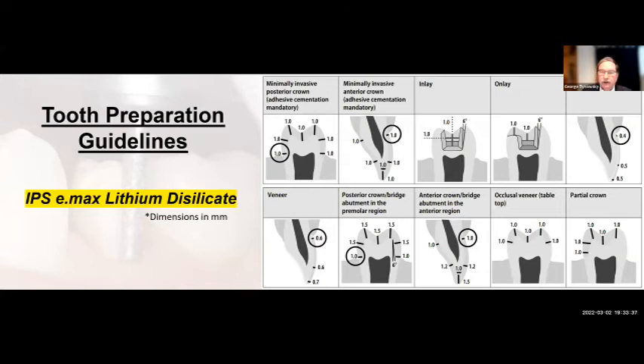Let's briefly take a look at some of the elements. We want rounded line angles and clearly defined margins, so the machine can visualize them from our scanning or impression techniques and can actually mill the margins accordingly. If we have an adhesive crown for lithium disilicate restorations, we can bond them in with a millimeter in place here. If we are using conventionally cemented restorations, then we would need 1.5, or if we're doing bridges, we need larger support for these areas.